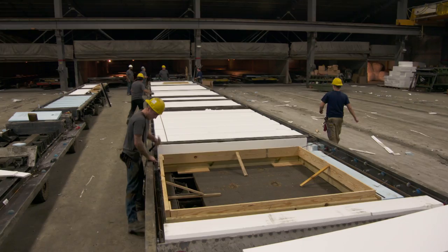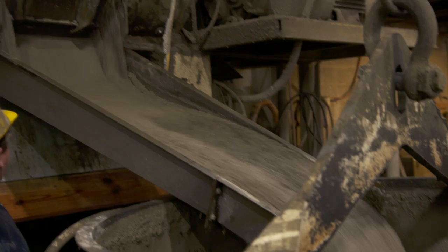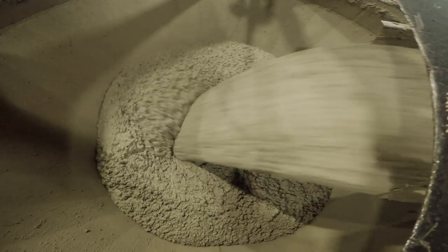This is where we mix our concrete — a 5,000 PSI mix. We have 100% control over the mix because we're in a climate-controlled environment. Typically on a job site you'll see 2,500 to 3,500 PSI, because they can't control conditions — trucks sitting, waiting to pour, adding water. The 5,000 PSI allows us to guarantee these walls to be watertight.